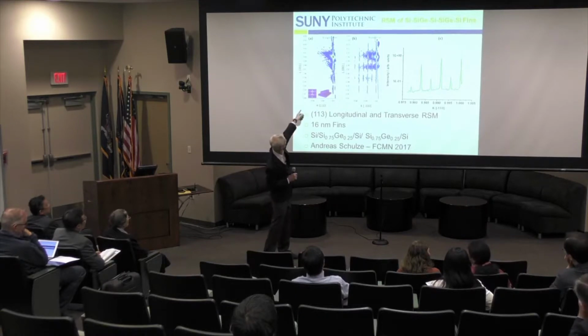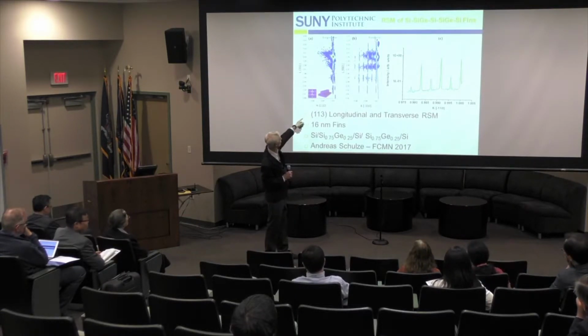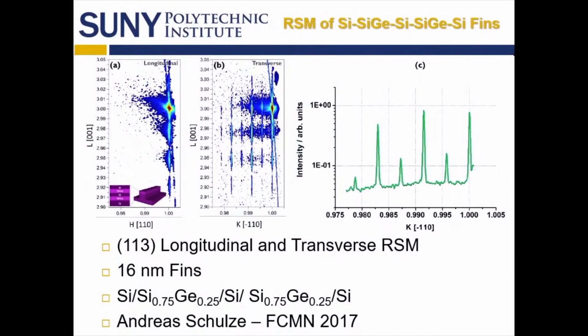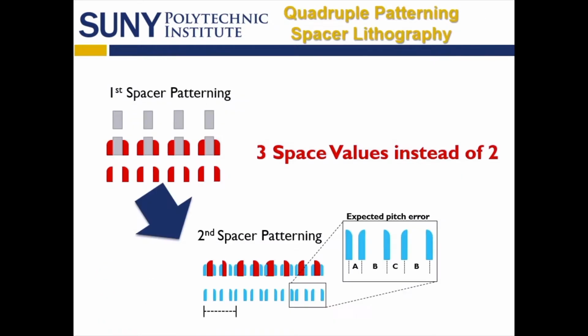All right. So anyway, if you just have the multilayer structure and you do a reciprocal space map, versus if you have the fins that are patterned, all of a sudden in the reciprocal space map over here, you can see in that X-ray diffraction pattern, it's a 113 for those of you that are really into X-ray diffraction patterns, you can see the satellite peaks, and there's a lot of information in those satellite peaks. These are for 16 nanometer fins, which was an older technology. But you can get information, and what you have to worry about is that silicon germanium relaxing.